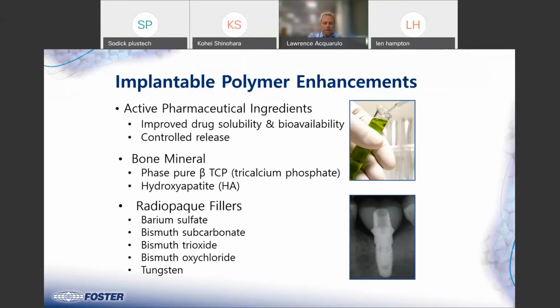That is a mineral that helps the bone regenerate or grow. So if you're implanting a screw into a bone, as the polymer starts to resorb, the calcium phosphate is there to help the bone strengthen and also fill the bone. You'll see TCP on its own, blended in the dental office, and it's used as a jaw bone filler. TCP has been used for years and years to support bone growth, and it's only really been maybe the last 20 years, 25 years, where it's been used in orthopedic. However, it's used a lot more now.